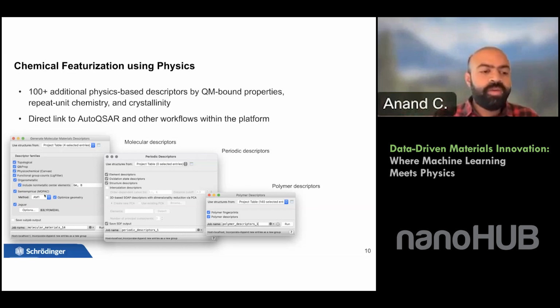If you want a faster descriptor, we can also calculate certain descriptors using semi-empirical approaches. For example, if you want a quick estimate of the dipole moment or the HOMO-LUMO value using MOPAC, you can get this using this panel. And if you want a full DFT calculation to get DFT level accurate descriptors, taking into account the geometry optimization and other steps in the DFT workflow, you can run Jaguar to get DFT descriptors. And once you have all these different descriptors, you can add them to AutoQSAR or DeepAutoQSAR as additional descriptors and run a machine learning model for that particular property. Similarly, for inorganic systems, you can generate some inorganic descriptors.